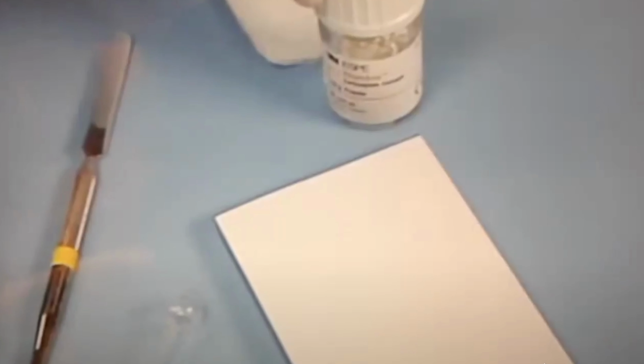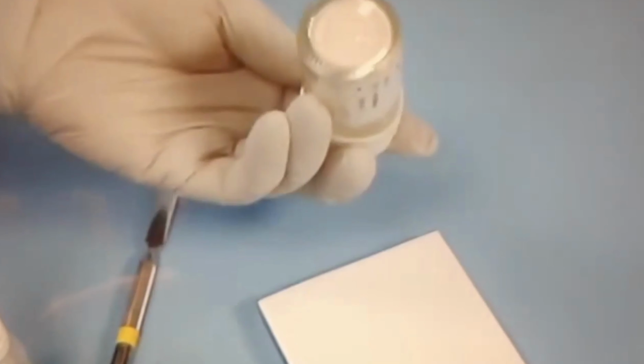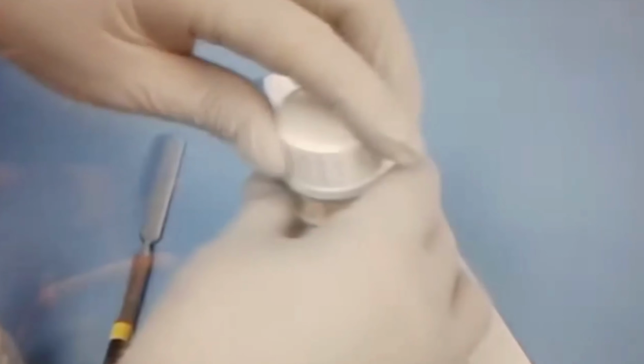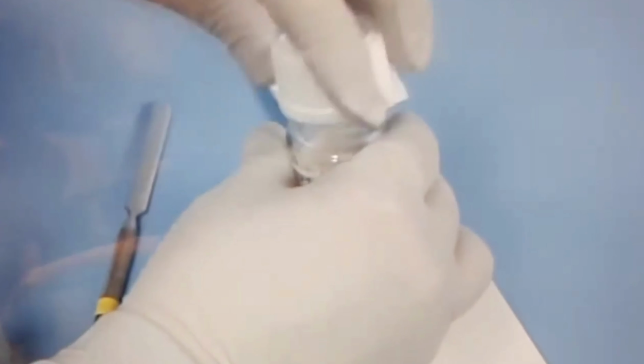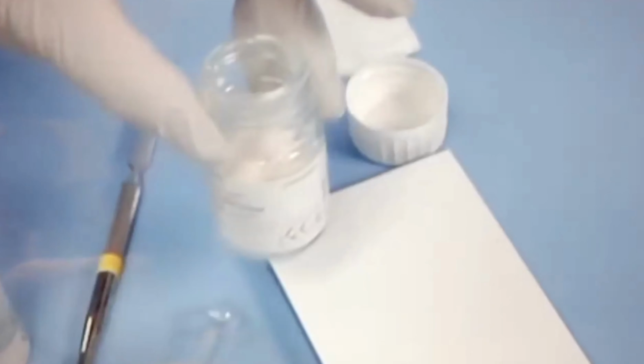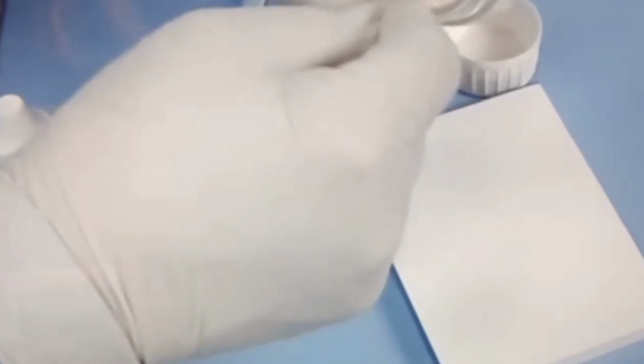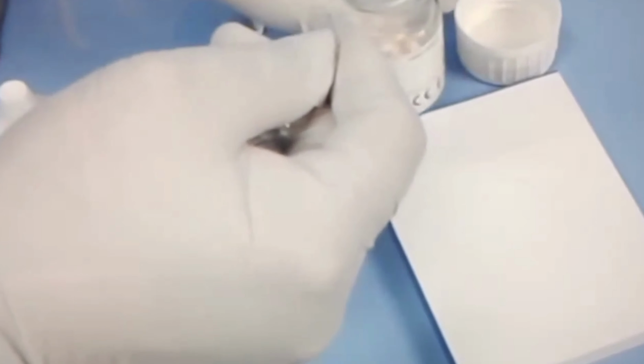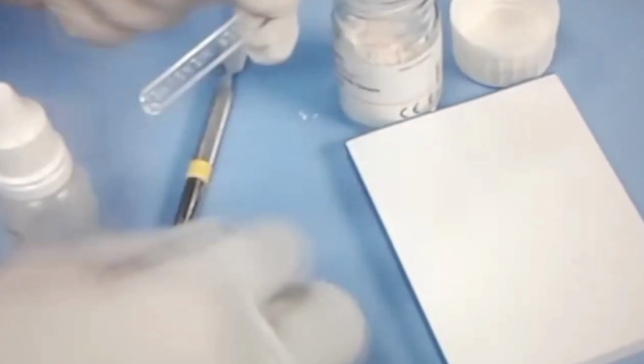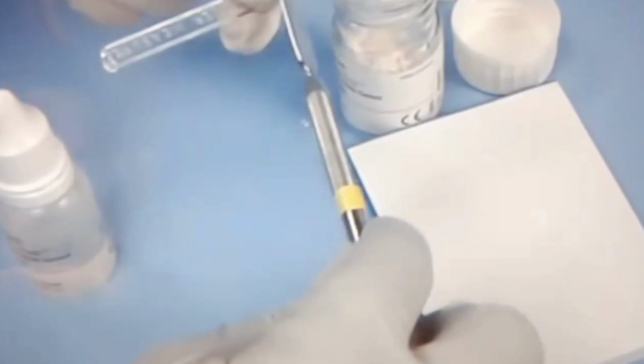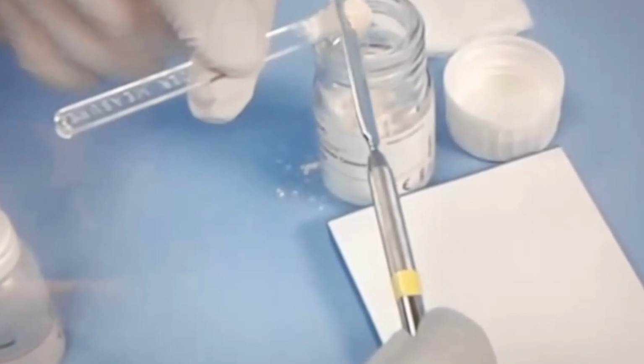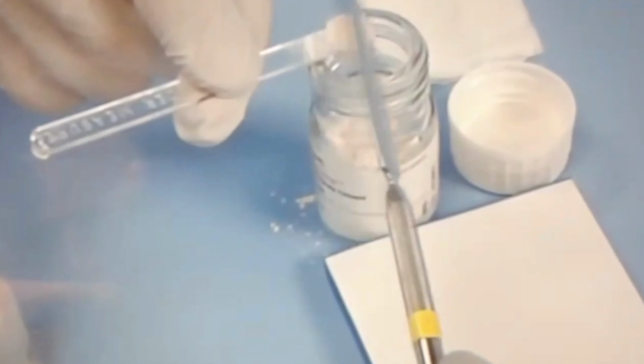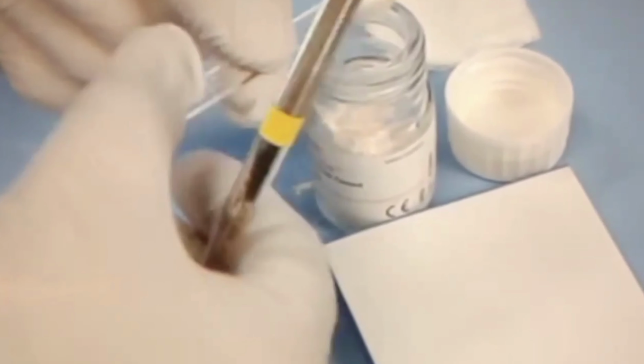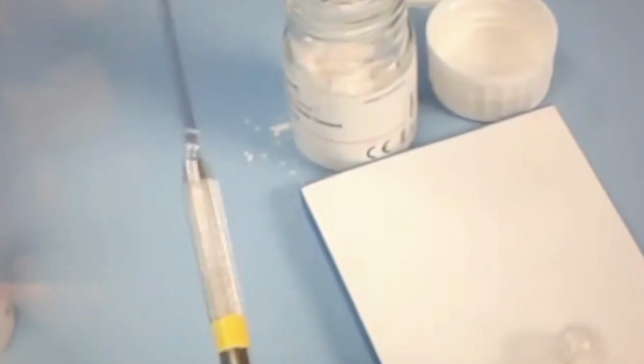Gather your material and supplies. Prepare powder by fluffing the bottle first. The recommended proportion for this material is 1:1. Dispense 1 scoop of powder, making sure to level the scoop with your spatula. Place the powder on one side of the treated paper pad.